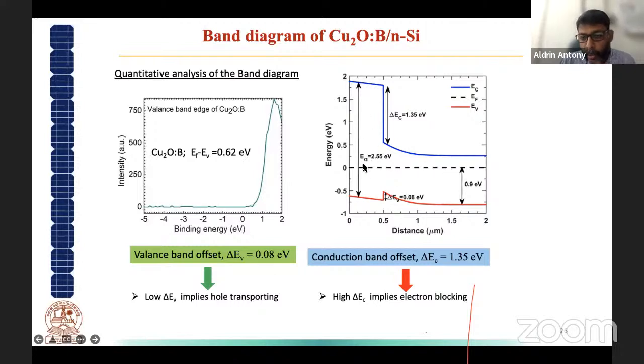And when it comes in contact with silicon, it shows a very small band offset of 0.08, which is very negligible for the p-type delta EV, which allows the holes to move in this direction, and it can move on to the contact of copper boron oxide. Whereas it forms a very high band offset, that is a delta EC of 1.35 electron volt, which blocks all the electrons coming into this direction.